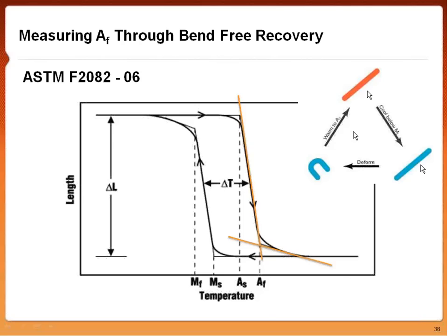But when you're watching it heat back up, you usually attach it to a weight. So say you've bent it and it's got the weight pressing down on it. As it starts to heat back up, it's going to push that weight, and you're going to be able to get a graph of length versus temperature. Then you're going to see when there's a drop-off between your length and temperature, and you're going to be able to draw tangent lines to figure out where your Austenite finish temperature is.